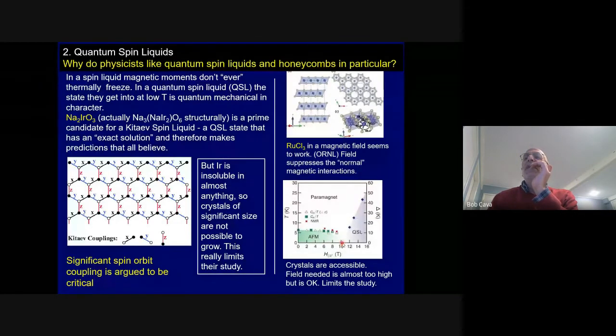The good news is that if you take that material in low fields, it spontaneously makes an antiferromagnet, and we'll see a picture of that in a minute. But as you apply a magnetic field to it, you change the ratio of interactions that are present in this honeycomb. You change the interactions to each other, and at around 10 Tesla, which is almost too high, but not quite, you can get this kind of bizarre magnetic state, which is called a Kitaev spin liquid. So that's the quantum spin liquid state. So the quantum spin liquid state shows up at around 10 Tesla in ruthenium trichloride. So that's the basis of this whole thing.